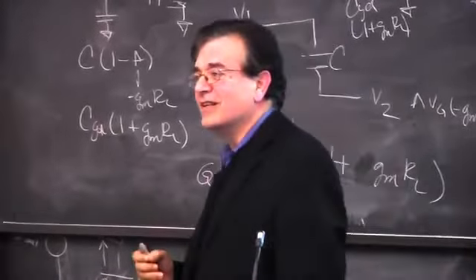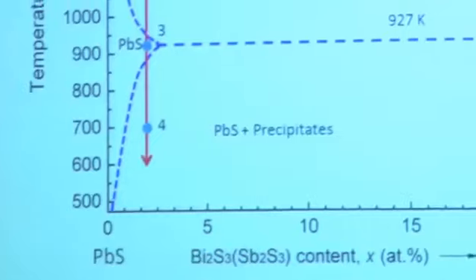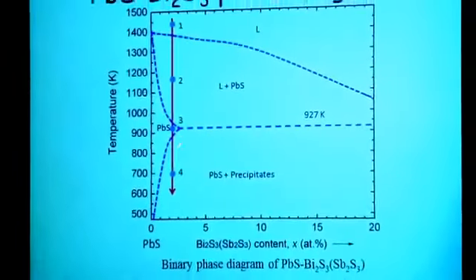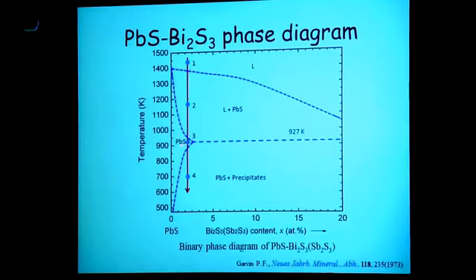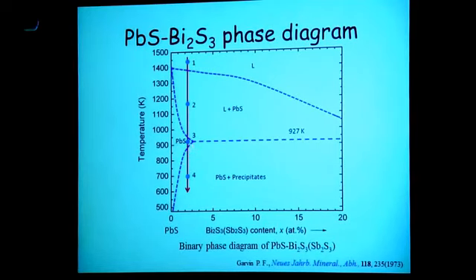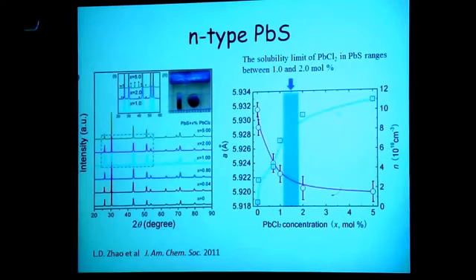So we said, can we nanostructure lead sulfide and see if we can make the thermal conductivity low? So we chose this system because we found a phase diagram that said bismuth sulfide is soluble in lead sulfide a little bit. And we thought, okay, if we can dissolve it here at this concentration and quench it and anneal it here, we will precipitate bismuth sulfide out and have a nanostructured system. What is the thermal conductivity of lead sulfide? Lead telluride, I said, is 2.2. Lead sulfide is 3.4. It's higher. So that's another reason why ZT is low. So we have more to fall from 3.4.